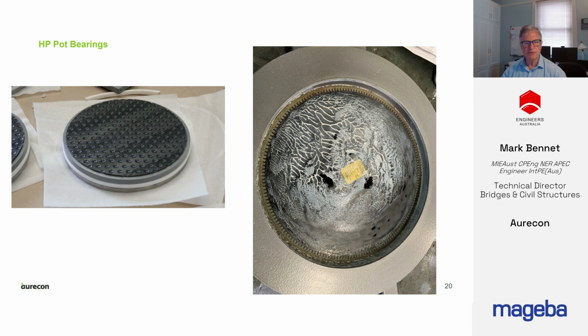There's a new generation of pot bearings, high performance pot bearings. They use the rubber pad with the POM chain seal, and they use an advanced sliding surface, not Teflon. In this case, this is ultra high molecular weight polyethylene. The sliding surface is dimpled to provide lubrication reservoirs in the top of the bearing. And with these features, the pressure allowed on the rubber pad and the pressure allowed on the sliding surface can be a lot higher than for conventional pots.